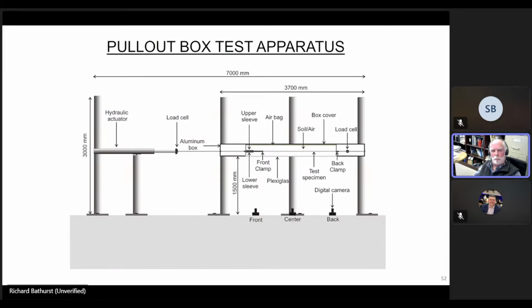So we built a pull-out box, a fairly large one, you can see by the dimensions here, 3.7 meters in length. And we embedded specimens of geogrid in this transparent soil. And we observed the behavior of the reinforcement by looking up through the bottom of this pull-out box, which had a transparent plexiglass base. And we could surcharge the specimen, and then we would pull on it as you would in a conventional pull-out box test. But the neat thing is we could watch what was happening.